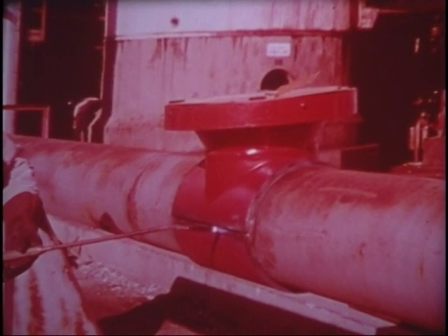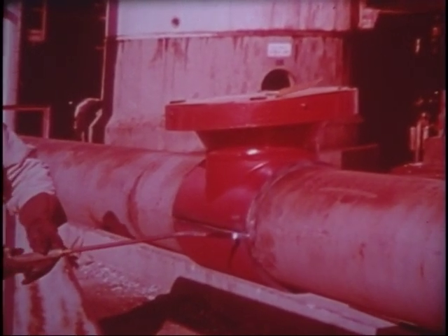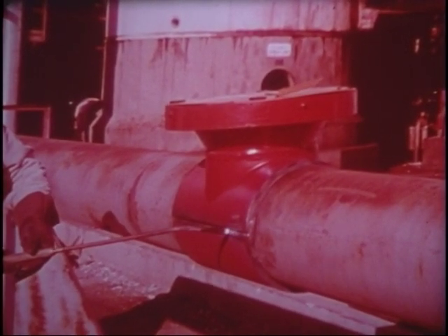Special care should be taken when welding is done on a pipeline carrying a product of a lower temperature than the outside atmosphere. Condensation can occur on the pipeline, causing weld cracks. This can be avoided by applying preheat to the pipeline.